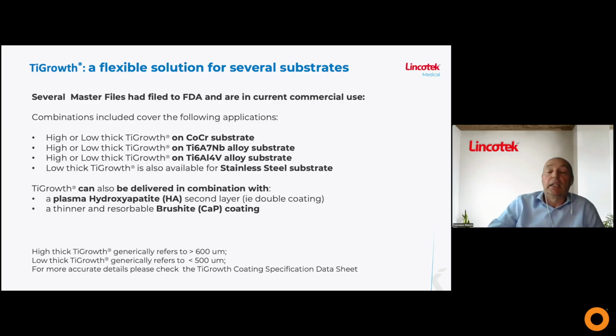And here are a number of different combinations of materials between the substrate and the coating itself, with the possibility to apply TiGrowth in high or low thickness on cobalt chrome, on different types of titanium alloyed with niobium or vanadium, and eventually also on stainless steel substrate. This is much more for hip implants rather than knee, like dual mobility cups. TiGrowth can also be delivered in combination with calcium phosphate in plasma spray format, so hydroxyapatite plasma spray, or in wet chemistry bioresorbable brushite, to further stimulate bone remodeling in the early phase.